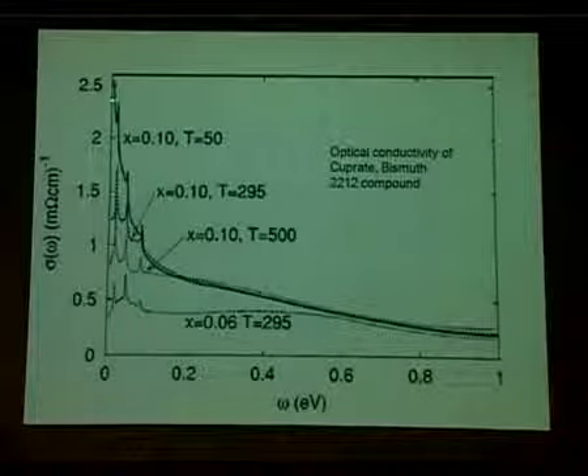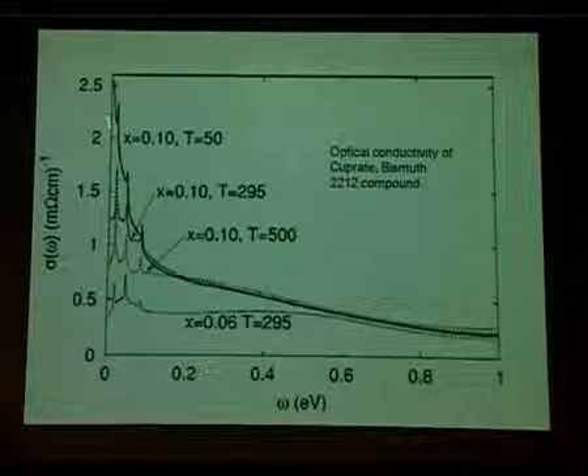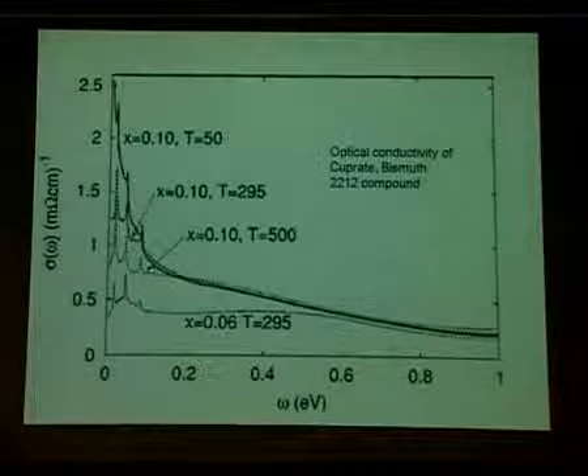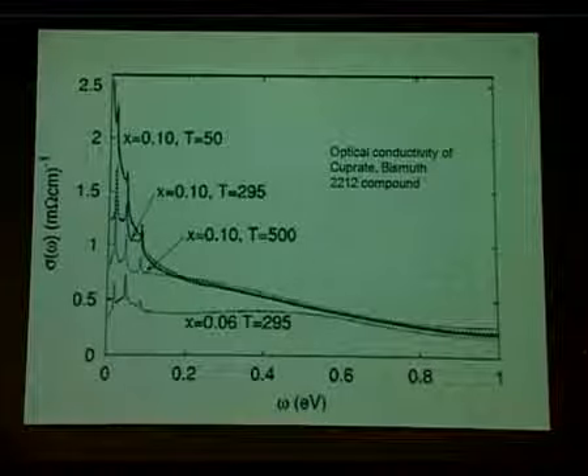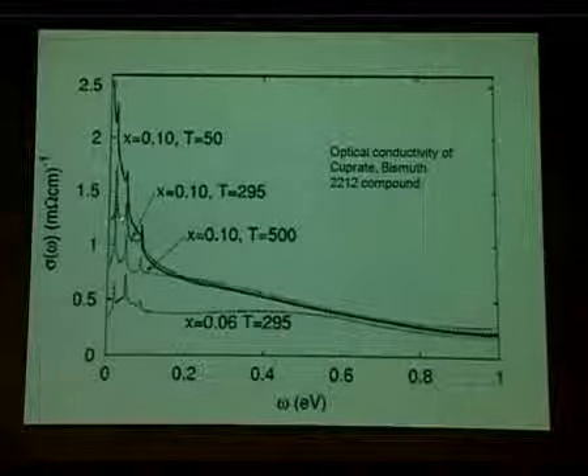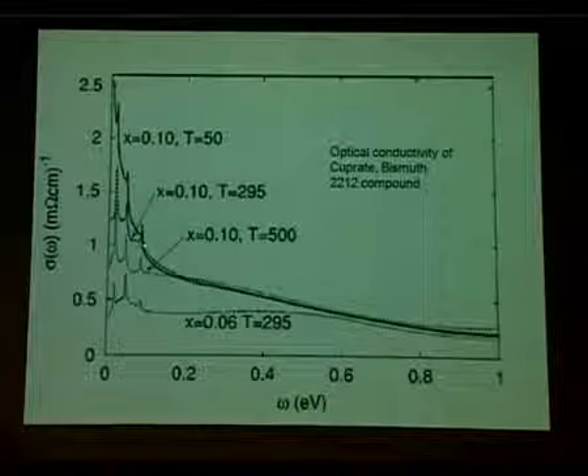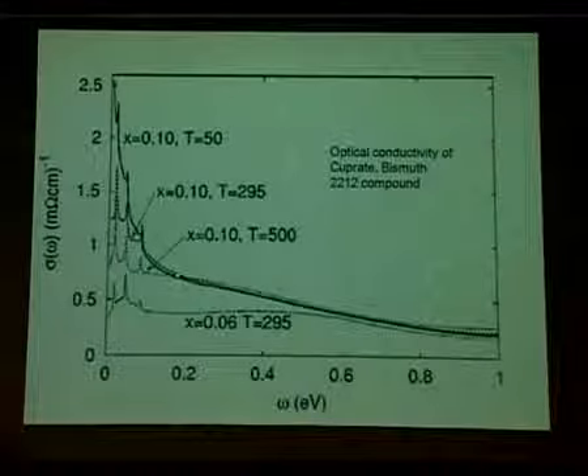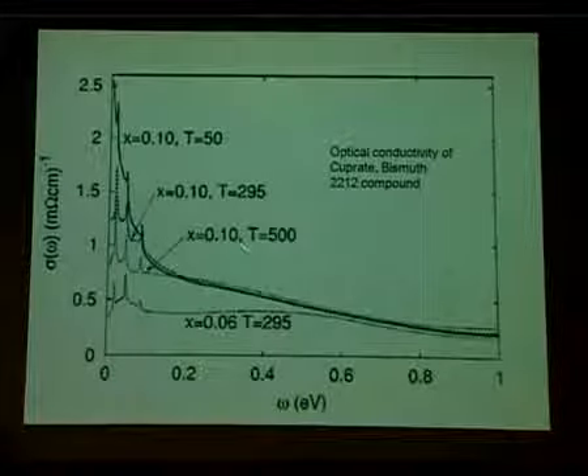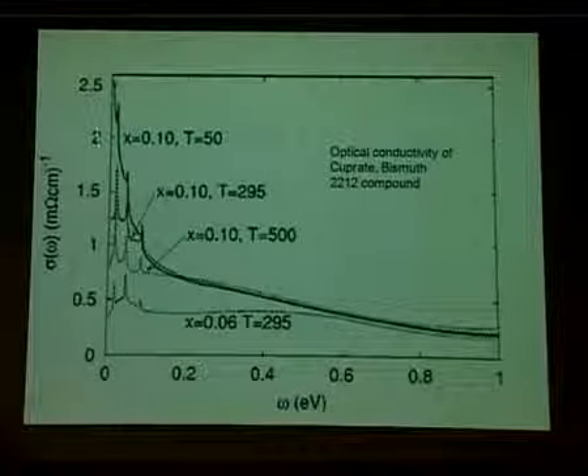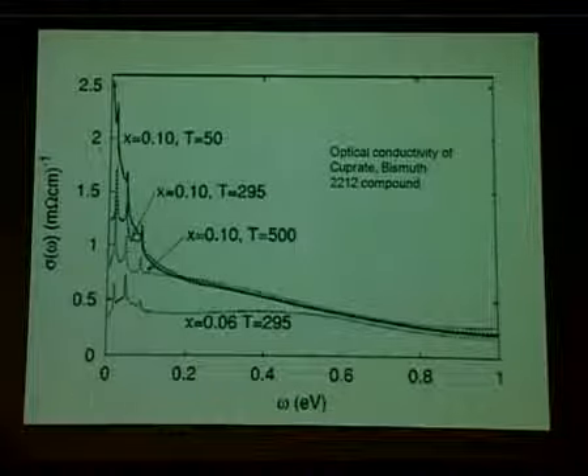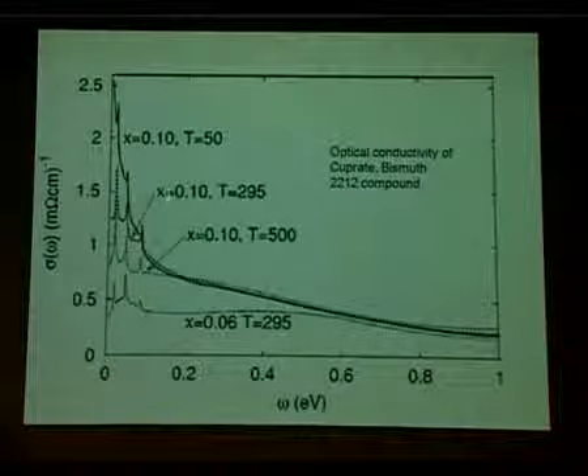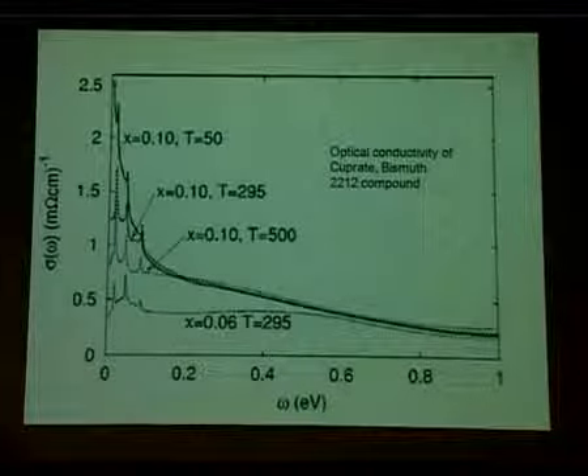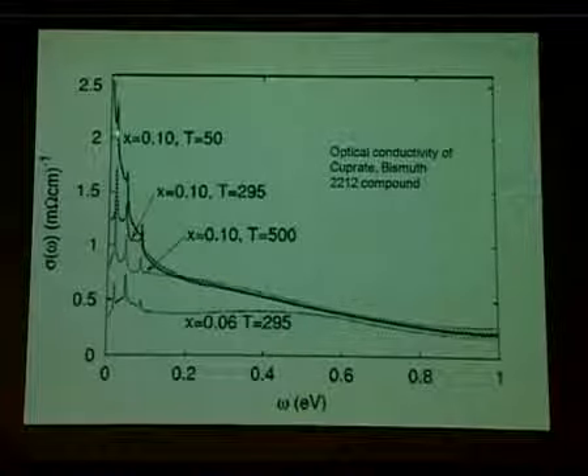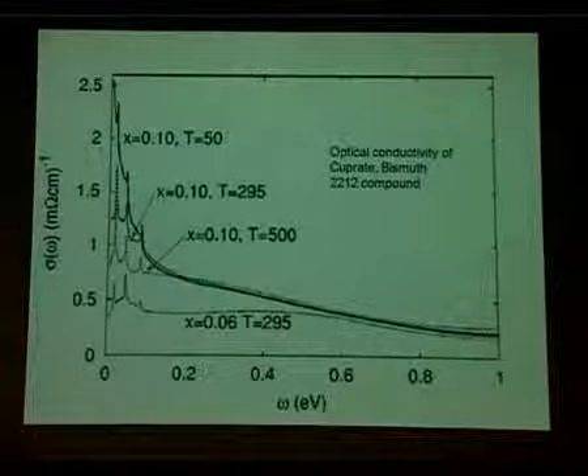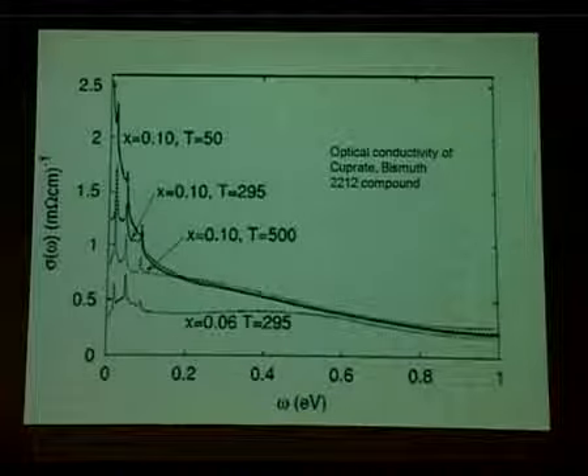And look at what happens. At 50 Kelvin, the conductivity is pretty large, and then suddenly it becomes small, and then it continues to be small. At 295 Kelvin, it is not that large, and then it becomes small again. And the conductivity here is exactly the same at all these temperatures. But what happens here at very low frequencies does depend on temperature. And the temperature scale on which it depends is very low, like 200, 300 degrees Kelvin. These spikes which distract our attention are due to absorption of light by lattice vibrations or phonons.